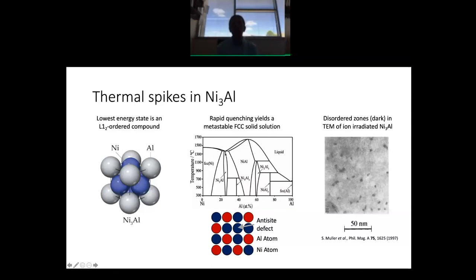However, if you were to go above the melting point, which is just over 1300 C, if you were to go up here into the liquid phase, those nickel and aluminum atoms take on random locations. So if you very rapidly solidify from the liquid into the nickel-3 aluminum, you get a disordered form of this solid, right? So rapid quenching from the melt causes this well-ordered nickel-3 aluminum to become basically a metastable face-centered cubic solid solution.